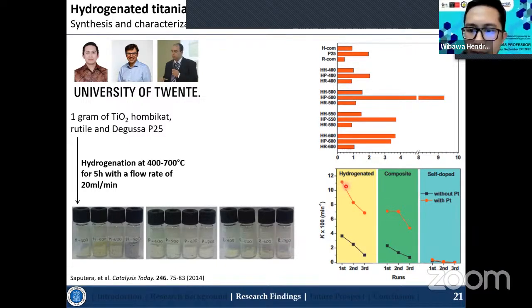And I also did the same thing, the stability of the catalyst, for the hydrogenated one. We can see that for the hydrogenated with platinum, the activity still significantly decreased from the first cycle until the third cycle, as well as for the hydrogenated without the presence of platinum.